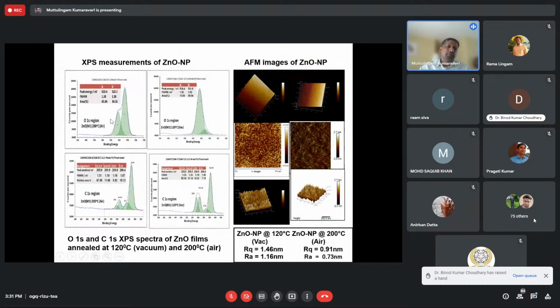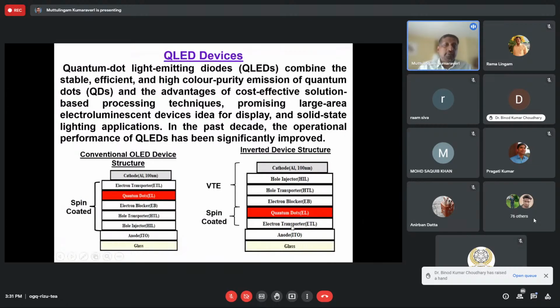And we run these two films for XPS and this AFM image. In the XPS, the O 1s region and C 1s region, we will see the difference. The XPS will help us find out the HOMO-LUMO position. And in this AFM image of these two, the 120 and the 200, when we anneal at 120, the roughness is 1.16 nanometer, but at 200 we get 0.73 nanometer. So these are the important things why we did the thin film characterization.